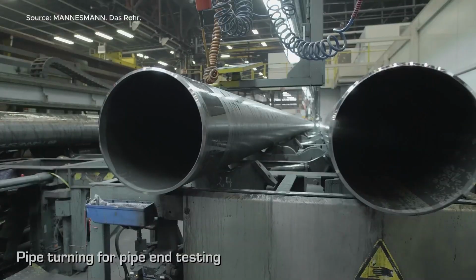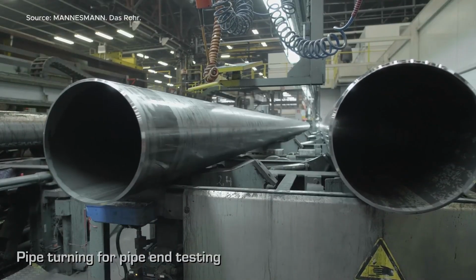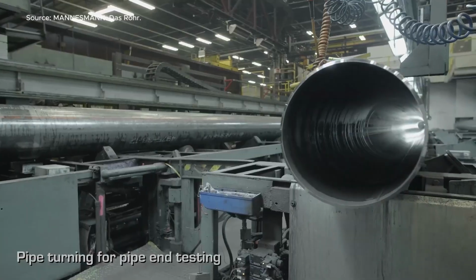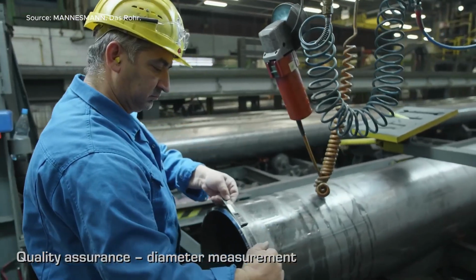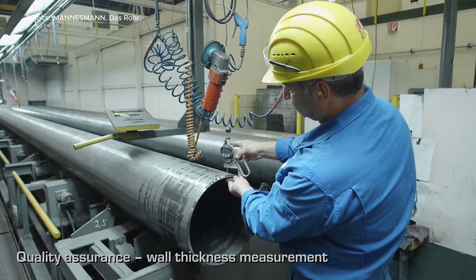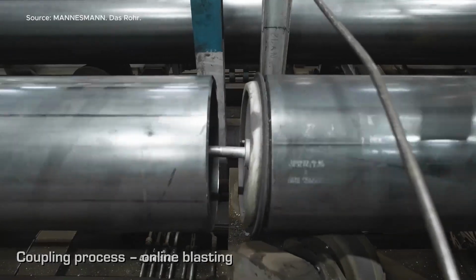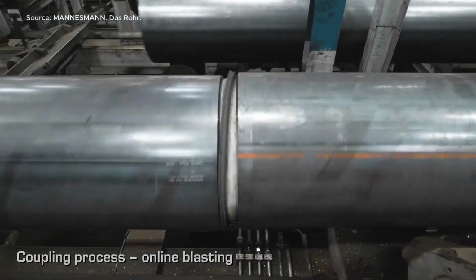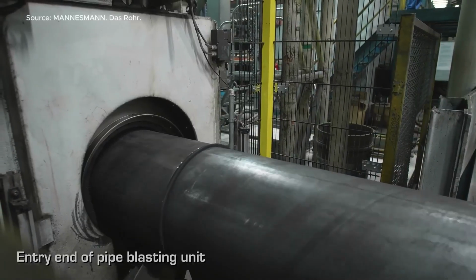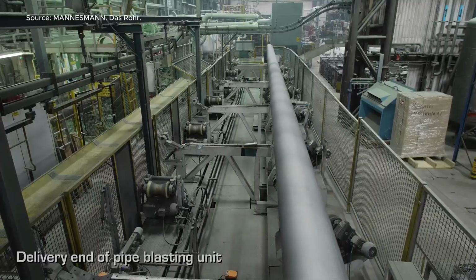The strip is formed into a tube and heated through high-frequency induction to around 1,600 degrees Celsius. The edges are then welded using HFI technology, followed by flash removal from the internal and external surfaces. The welded pipe is heat-treated, straightened, and sized to precise specifications.